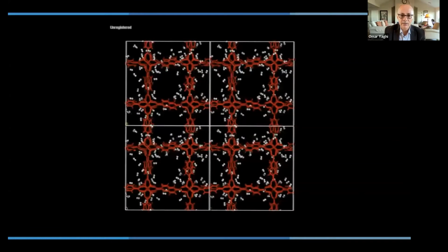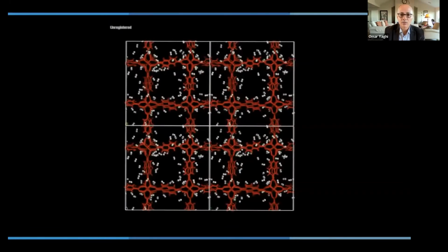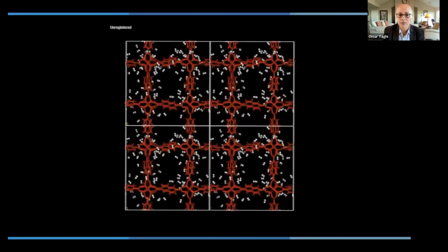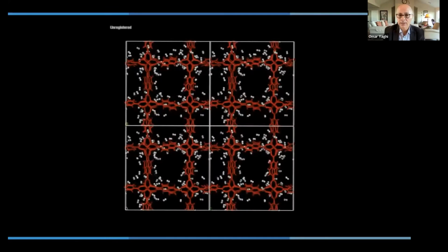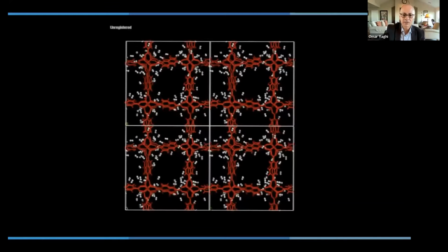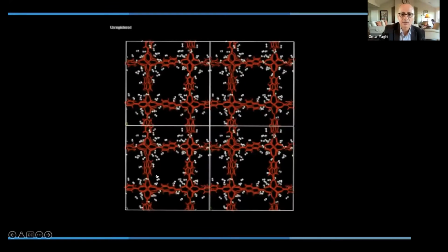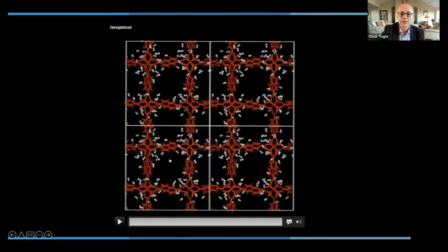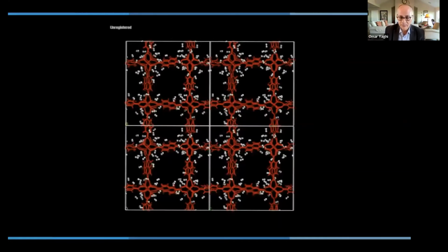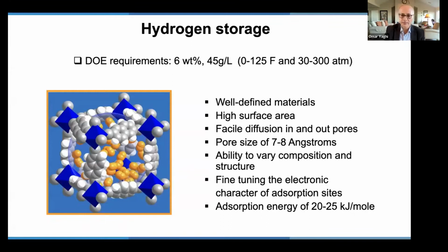And its interaction with the framework allows you to pack the hydrogen molecules closer to each other, much closer than they would be without the MOF. In this case, you see that the hydrogen molecules are aggregating around the framework, and we use interpenetration to fill these pores with additional adsorptive sites.